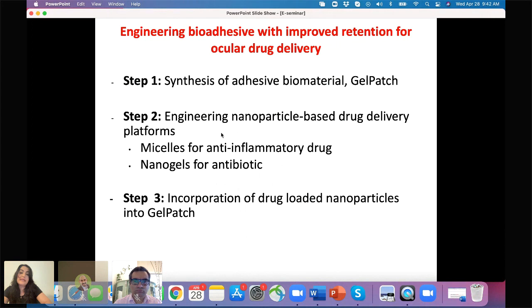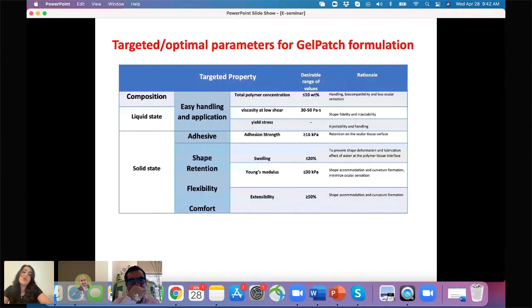Once we form these nanoparticles and we optimized GelPatch formulation, in our third step, we incorporate our drug-loaded nanoparticles into the GelPatch. And then here are some targeted or optimal parameters for the GelPatch formulation. We use experimental design software, JMP, to optimize different properties of the GelPatch. And at the beginning, we summarize what are the required properties for our GelPatch formulation. Basically, there should be some characteristics at the liquid phase, and some specific characteristics are required in the solid phase.